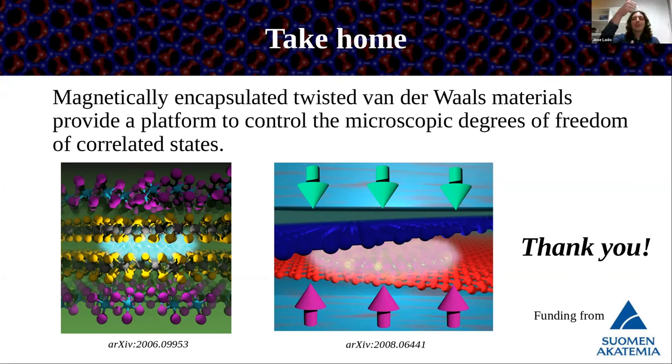Yeah. So in the case of the ferromagnetic configuration, you can think that this is effectively as if you were applying a magnetic field and essentially lifting the spin degeneracy. So that is, let's say, the simplest case to understand. Ferromagnetic configuration essentially creates a spin splitting of your four bands. Initially, you have four, you get your spin splitting, you get two. In the antiferromagnetic case, that's a little bit more complicated to understand, and I would say that there's not a simple argument for that one. You can understand from symmetry that in that case you are going to lift the other degree of freedom. But of course, you don't know for sure that you are going to get isolated two-fold degenerate bands.